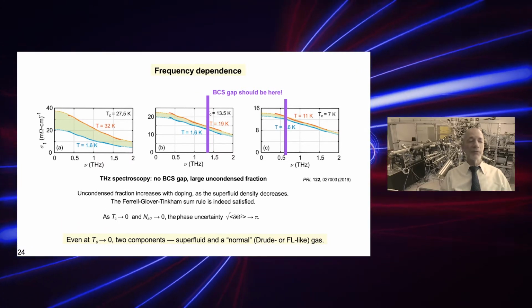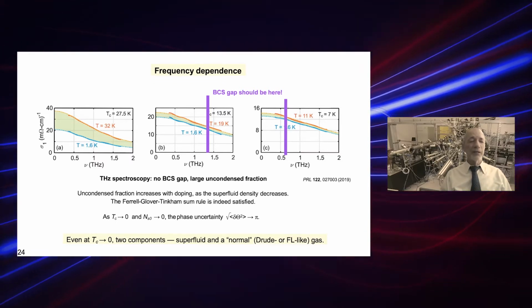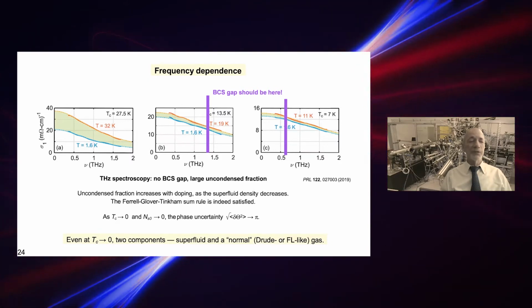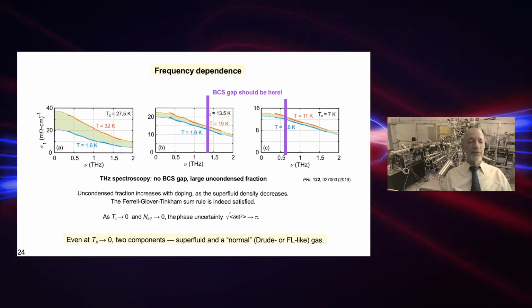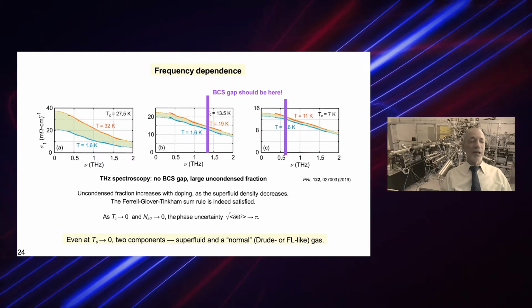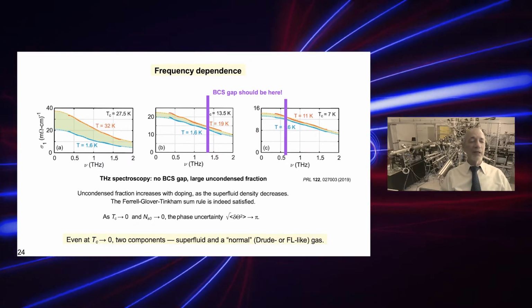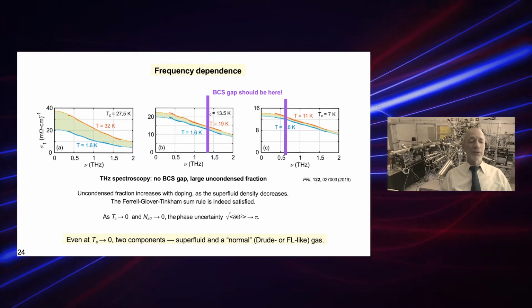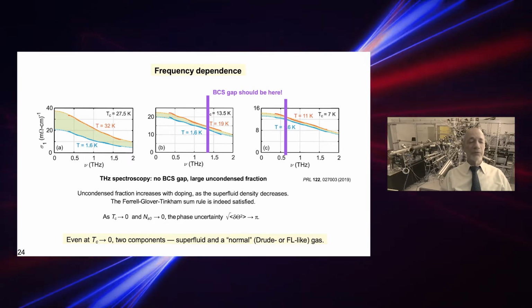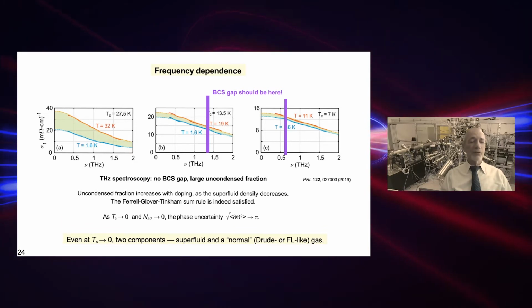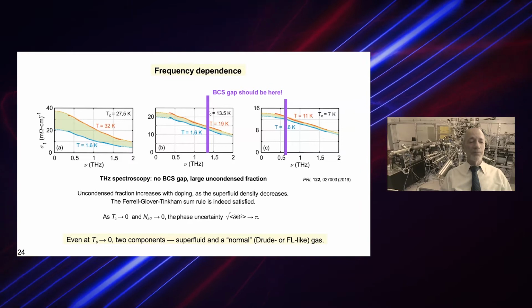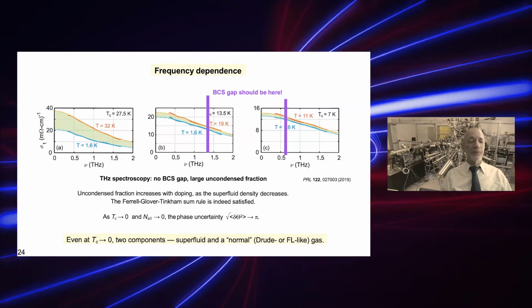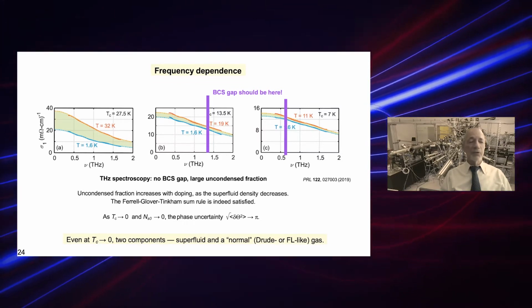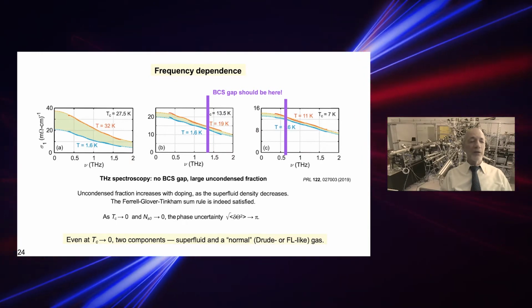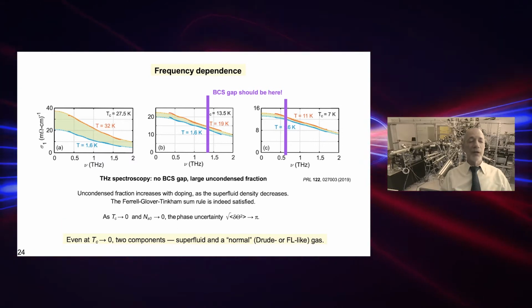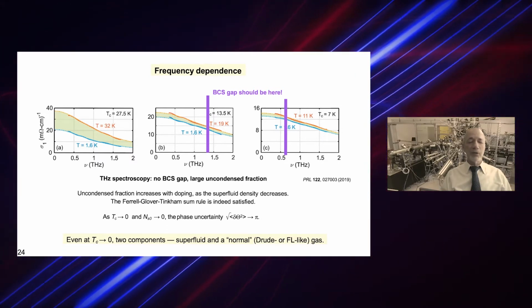Their key findings are as follows. First, the superconducting gap is not seen where it should be expected from BCS theory. Second, the drop of spectral weight starts at an energy that is as much as 10 times higher than the BCS value, indicative of very strong pairing interaction. And the third and most surprising is that the drop is only partial. The loss of spectral density is small. It goes into superfluid, and it's accompanied with the increase of a residual Drude-like conductivity due to normal electrons. And this is present even at temperature close to zero.